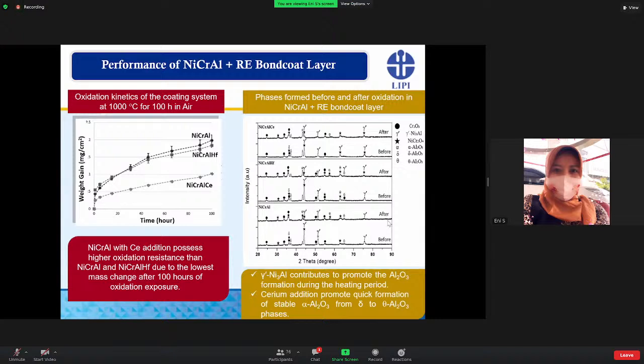The phases before the oxidation were identified to be a mixture of delta alumina, alpha alumina, theta alumina, accompanied by spinels, chromium oxide, and gamma prime nickel 3 aluminum. Nickel 3 aluminum in the samples promotes the quick formation of alpha alumina from delta to theta. So according to this result, it clarifies that the addition of cerium in the nickel chromium aluminum can modify the oxide growth process, making the sample more protective against high temperature oxidation.